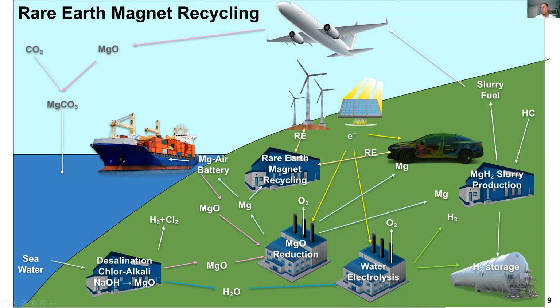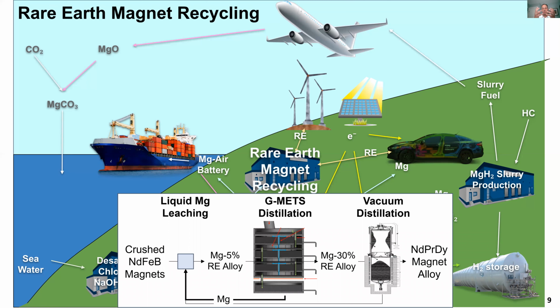Moving on, a criticism of wind turbines and hybrid electric and hydrogen vehicles is that they use rare earth permanent magnets in the motors, shown here as RE, or in the wind turbine generators. These magnets require neodymium, praseodymium, and dysprosium metals, which are currently produced using very dirty processes in China. There is currently no post-consumer rare earth magnet recycling. Liquid magnesium is a great leaching agent to recover the rare earth elements out of magnets for recycling. But separating the rare earth magnesium alloy is a challenge. Once again, multiple effect distillation is usable to do this separation, and it reduces the overall flow sheet energy consumption by 70% and overall capital and operating costs by 50% compared with traditional vacuum distillation.